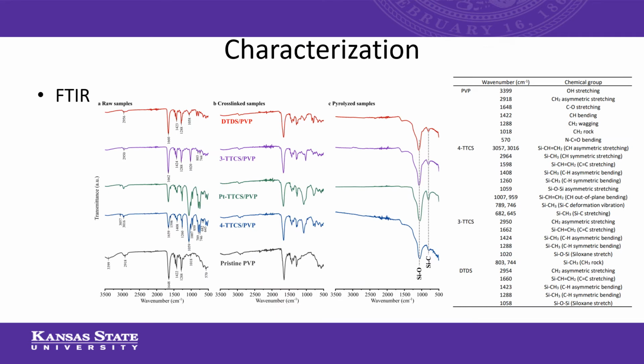FTIR is performed to determine the cross-linking behavior of the samples. We did the pristine PVP first to confirm that PVP doesn't get involved in this cross-linking process. And then you may see that for all samples, the characteristic peaks have decreased but not completely disappeared, which means that the cross-linking happened but not completely happened in the samples.